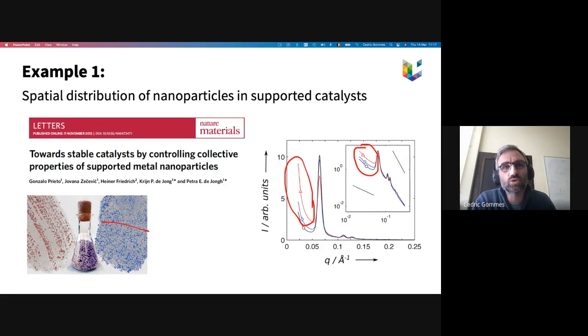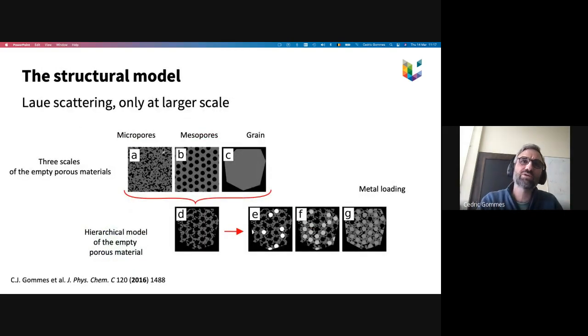And to really capture this, we have to build a model that accounts for the various structural levels in the porous material. Of course it has an ordered mesoporous structure, but between neighboring mesopores, you also have micropores, and the mesoporous structure does not extend forever, it's in the form of grains. And then once you have these models for the porous material itself, then you can model the metal loading. There we just had a one-parameter model, basically telling you whether all the material is concentrated into a few pores or homogeneously distributed.